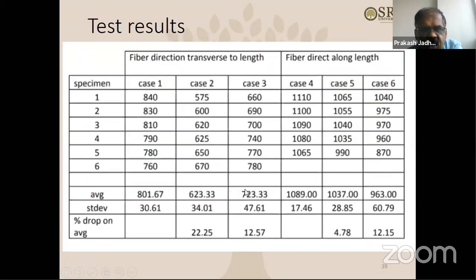Okay. And of course you can see the tabulated charts for the test results. These are the failure loads and average and standard deviation. And then ultimately what we show here is if you compare case one and case two. Case one average failure load is 801 and case two average failure load is, this is ultimate failure load, not initiation, okay, ultimate failure load. So case one shows the ultimate failure load of 801, case two shows the average ultimate failure load of 623. So if you compare this, you get a drop of almost 22% in failure load.